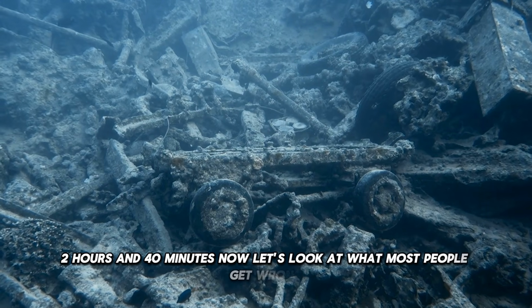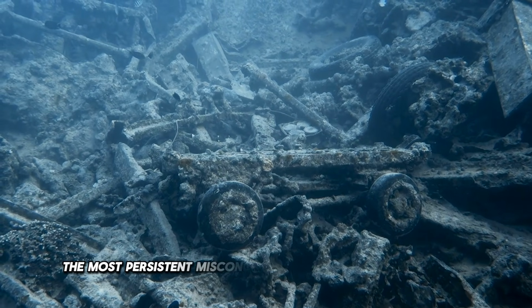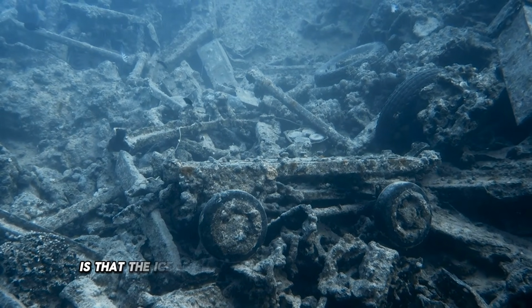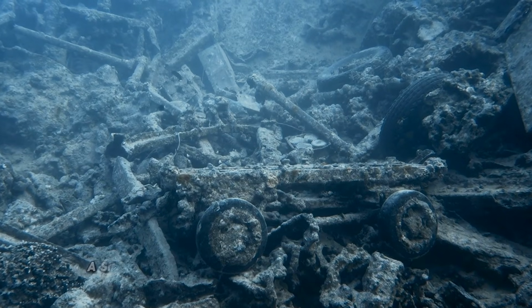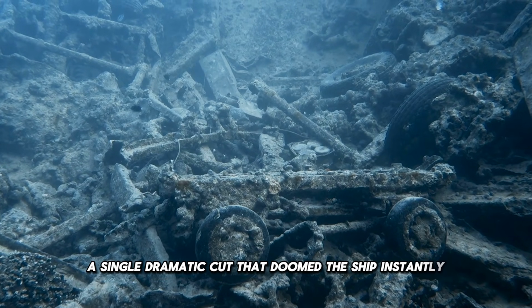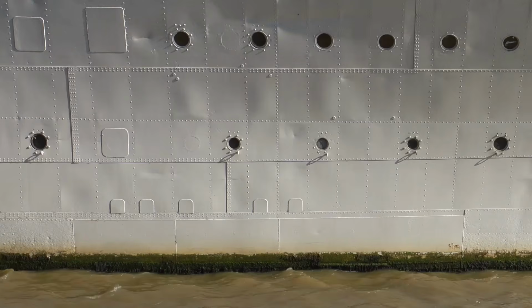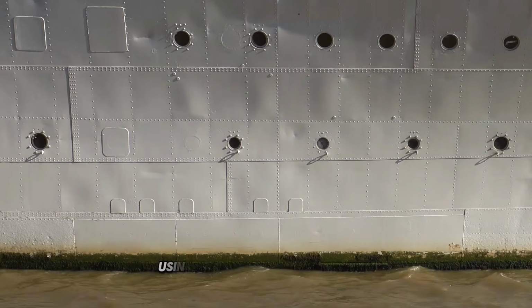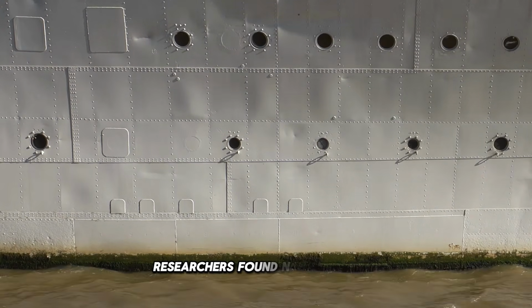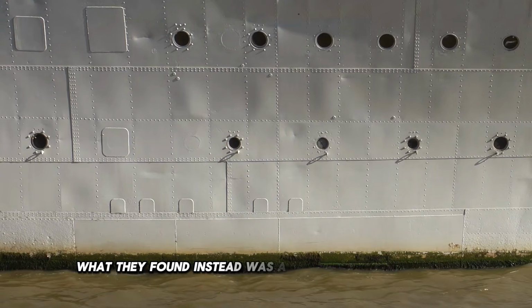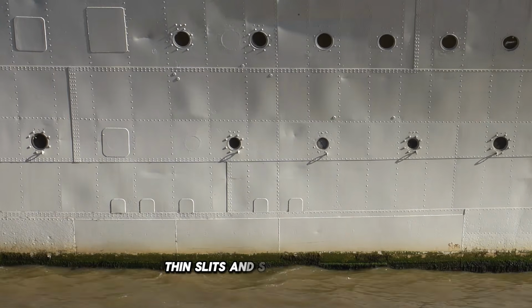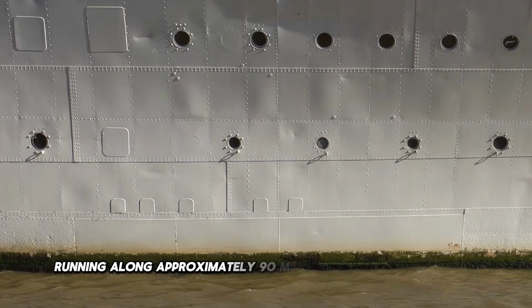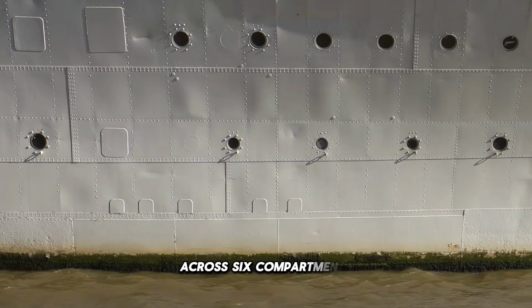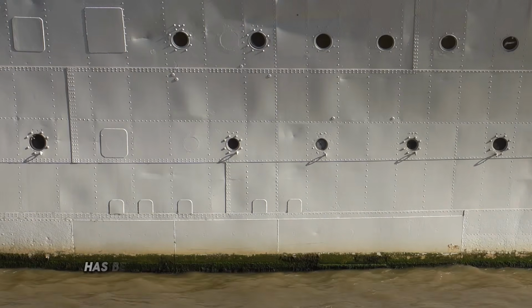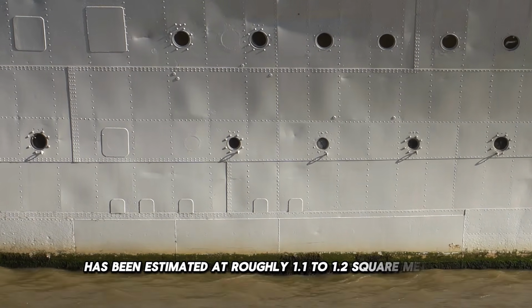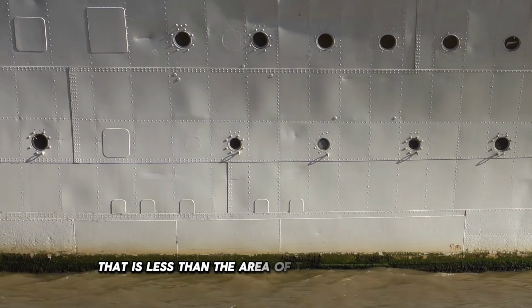Now let's look at what most people get wrong. The most persistent misconception about the Titanic disaster is that the iceberg tore open a massive gash in the hull, a single dramatic cut that doomed the ship instantly. That is not what happened. When the wreck was surveyed in detail in the 1990s using sonar and remote imaging, researchers found no large gash. What they found instead was a series of small openings, thin slits and separated seams, running along approximately 90 meters of the starboard hull across 6 compartments. The total area of those openings has been estimated at roughly 1.1 to 1.2 square meters. That is less than the area of 2 standard doors.